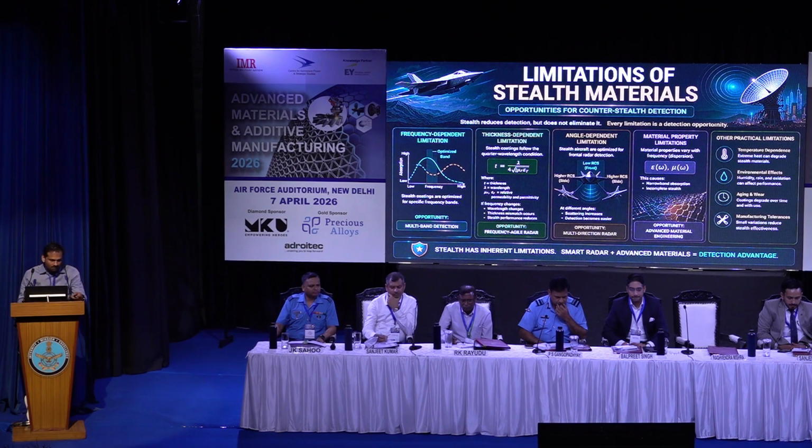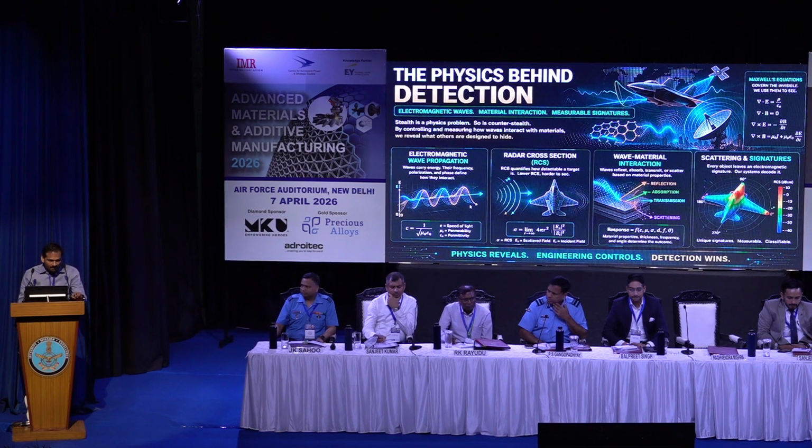Next, we know the electromagnetic wave has two components. In most cases we forget this; previously they mentioned using graphene. Graphene is electrically conducting, CNT is electrically conducting. Electrically conducting materials have free surface charge, so they can reflect and can only react with the electrical component of the electromagnetic field. But we have to suppress both fields, so we need a material that responds to the magnetic field.